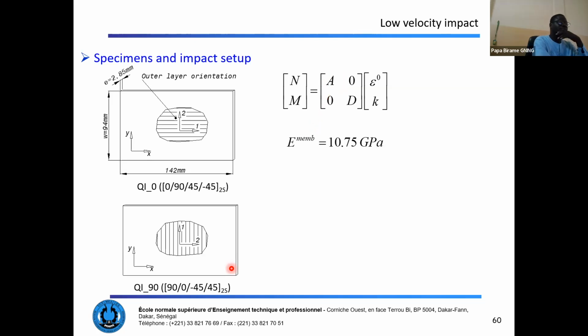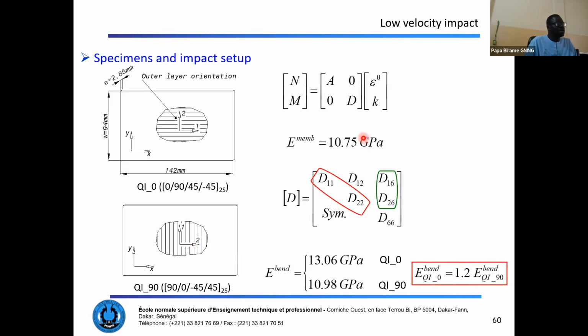So let's test flax epoxy composites in impact. The laminates that were chosen were quasi-isotropic layups. It was the same layup, but when we look at the outer orientation, one was parallel to what was called the x-axis, and the second was perpendicular to the x-axis. This change of positioning makes the membrane rigidity the same for the two specimens, but the bending behavior differs by around 20% because of the positioning of the outer layer.